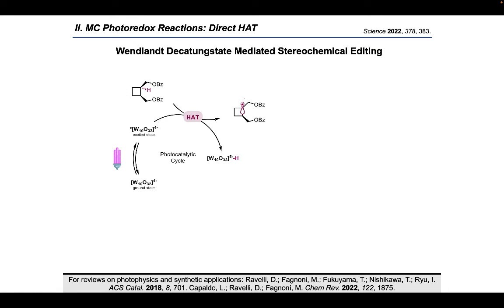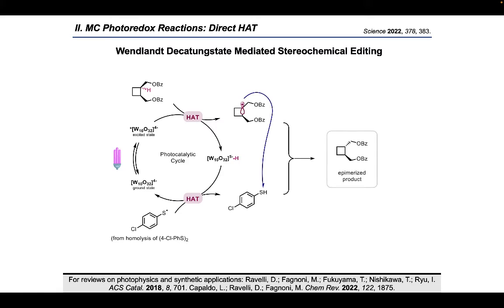Thus, in the presence of a substrate such as this cis-1,2 disubstituted cyclobutane, the methine hydrogen will be abstracted to furnish the protonated monoreduced form of the decatungstate catalyst and the key alkyl radical species. A disulfide co-catalyst that homolytically cleaves to give a thiol radical helps to return the decatungstate photocatalyst to its ground state, and the resulting thiophenol then serves as the H dot source to furnish the desired epimerized, thermodynamically favored product and to regenerate the thiol co-catalyst.